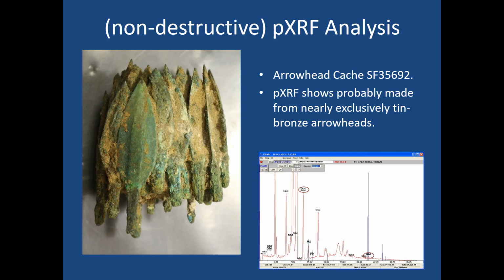Christina started off her work with non-destructive analyses using portable X-ray fluorescence analyses. These were able to tell us at a basic level the different kinds of alloys that are being used. Here's a beautiful cache of arrowheads that was found at the site. Being able to take the portable X-ray fluorescence machine, aim it at these arrowheads and record their composition told us that they were largely made of tin bronze. They were fairly consistent in their composition. You can see an example of an X-ray spectrum generated by this technique on the right-hand side.